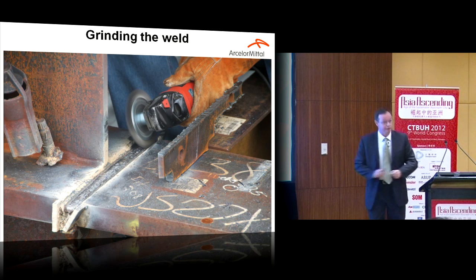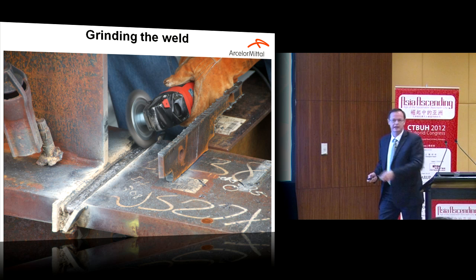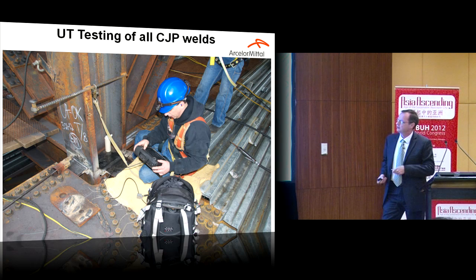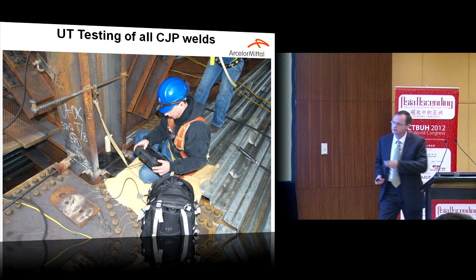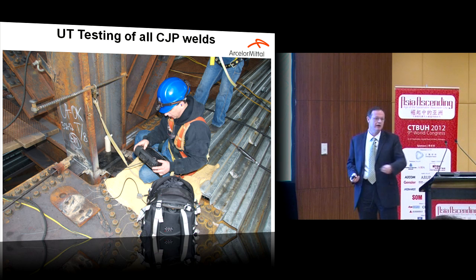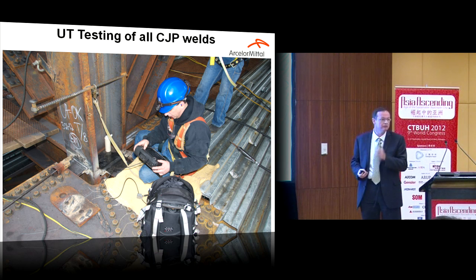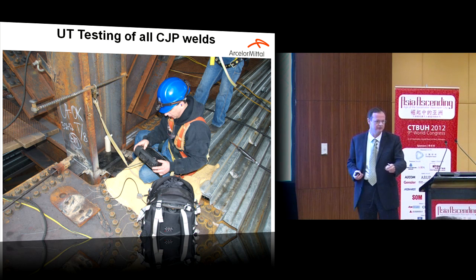After that, you also need to grind the weld to make a smooth weld and to do the next pass. And after that, there should be an inspector on the job site who will do a UT test. If you have a full penetration weld, you must do an ultrasonic test.